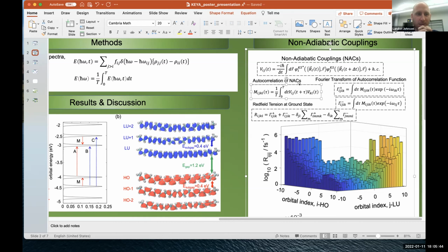Yes, because the autocorrelation function drops off basically immediately. So although the theory instructs us to take the interaction matrix elements at time t and t plus tau at different time spots, we see that they are non-zero only if the time delay tau is 0 or very close to 0, which makes practical life much simpler.